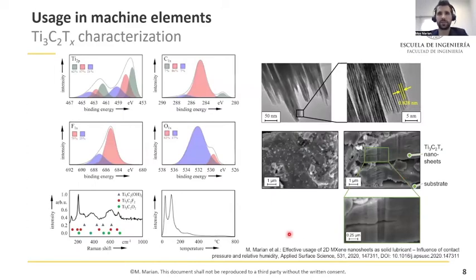Here we see some results from material characterization of fabricated MXene nanosheets and coatings. On the right are HRTEM images where we can observe the regular and multilayer character of the nanosheets. Below we see some SEM images after coating by drop casting. On the left is the surface from above, and on the right-hand side we can see some focused ion beam milled cross sections. There we see that the MXene layer deposited on the substrates consists mainly of multilayer nanoparticles or nanosheets, where we can also observe the characteristic accordion-like structure.